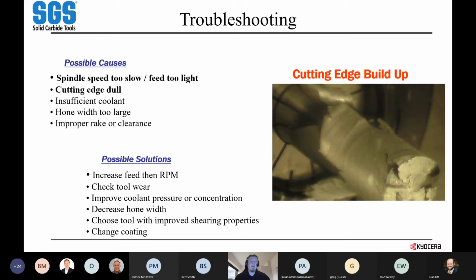So you can try increasing your feed rate, then play with your RPM. Make sure the tool's not worn. Get your coolant positioned how it should be, in the most effective way possible to be in around the entire cut, and then you can also look at playing with different geometries and different coatings if that doesn't work.